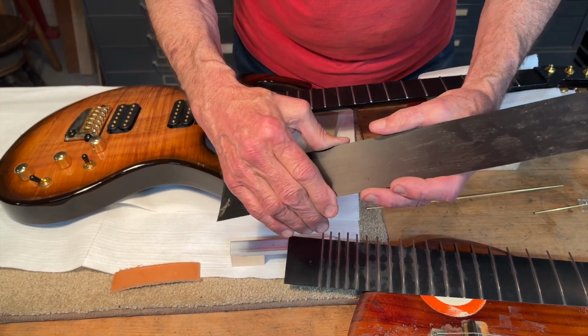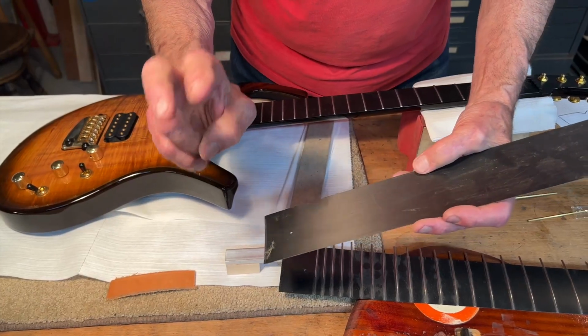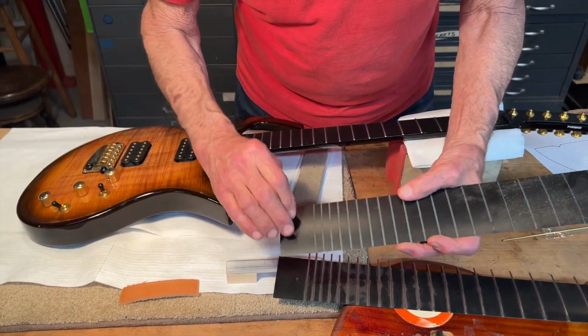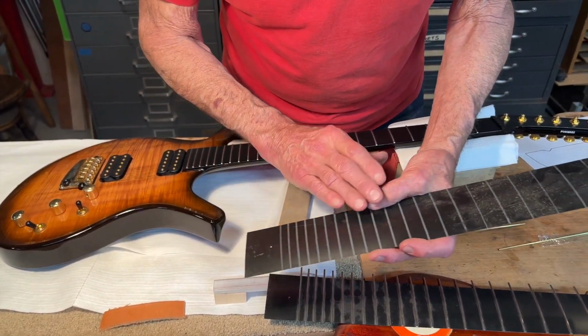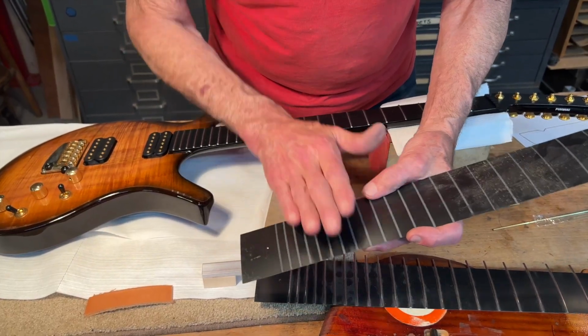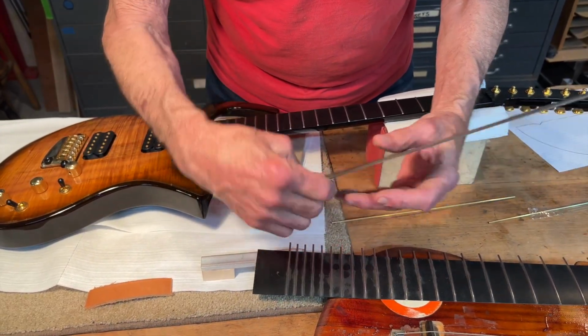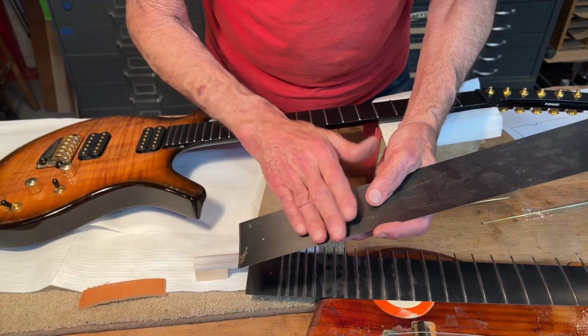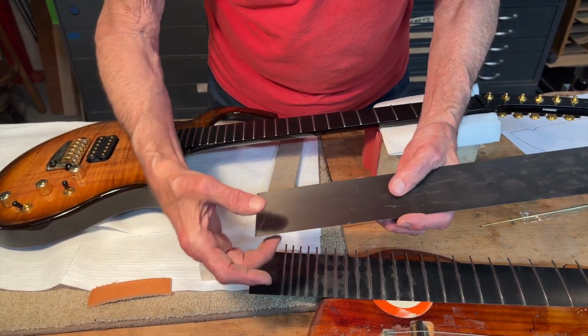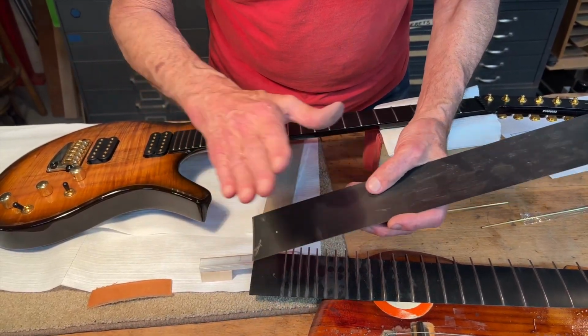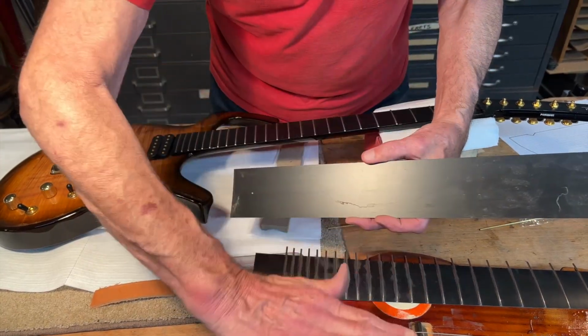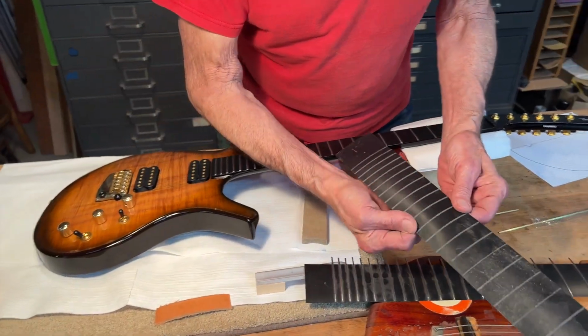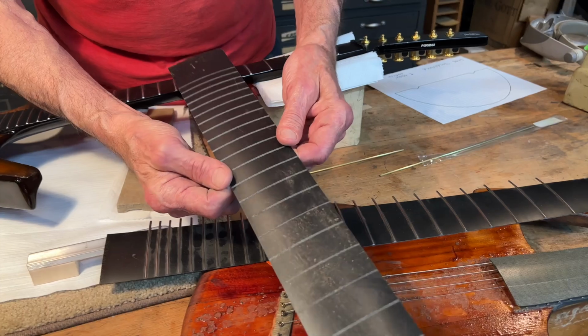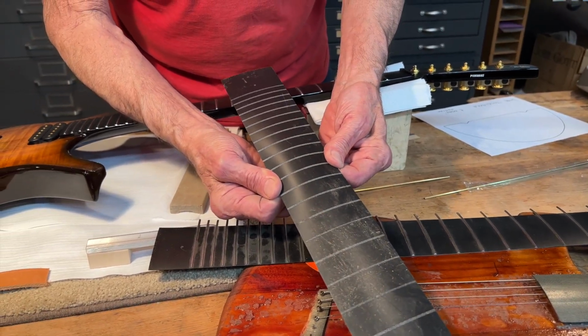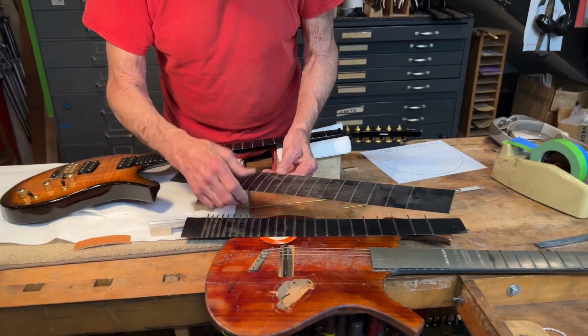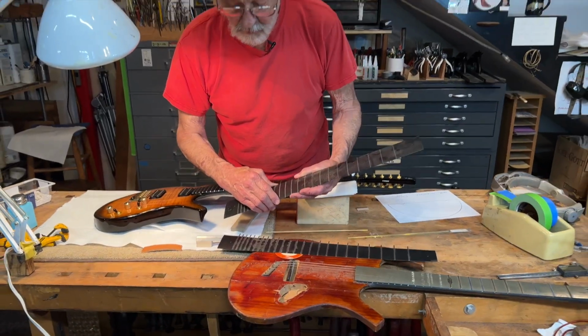And then something that we got for free, so to speak, was because we laminated an unbalanced layup. In other words, there were cross-grain fibers in the fiberglass cloth and no cross-grain fibers on this side. Again, half carbon, half glass. When we took it out of the press, it automatically sprung into a curved shape like this. And so it was already wanting to curve in the correct direction for guitar fingerboards.